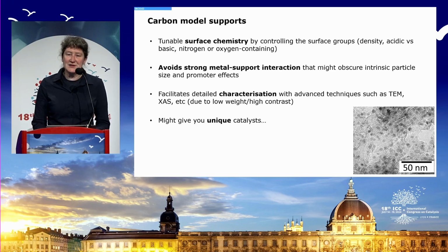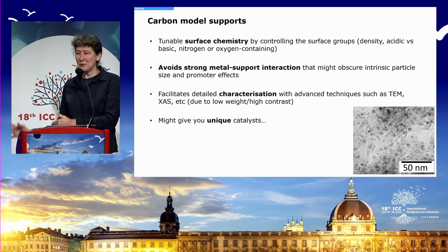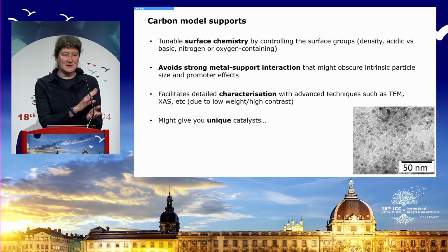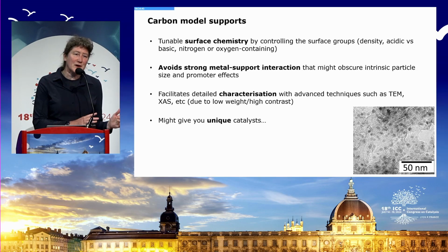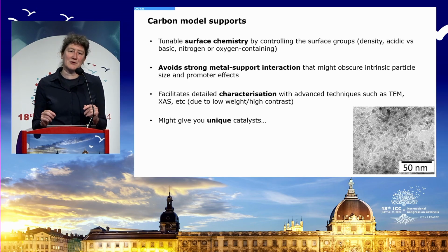So in this presentation, I'm going to give two examples in much more detail, and both of them I'm using carbon supports. Carbon supports are one of my recent favorites, I would say, also for the preparation, because with carbon supports you can tune the surface chemistry. You can make them acidic, you can make them alkaline, you can put a high density of surface groups with oxygen or with nitrogen, and this helps you also in the preparation to tweak things like the particle size.